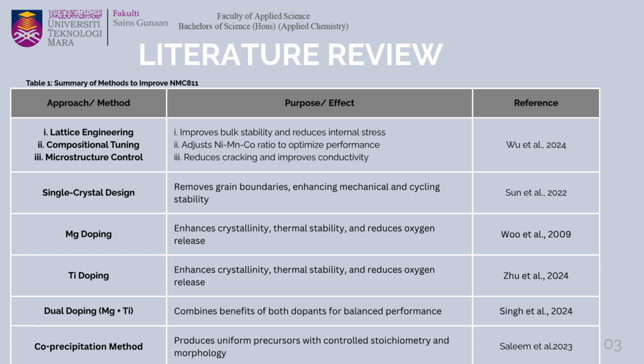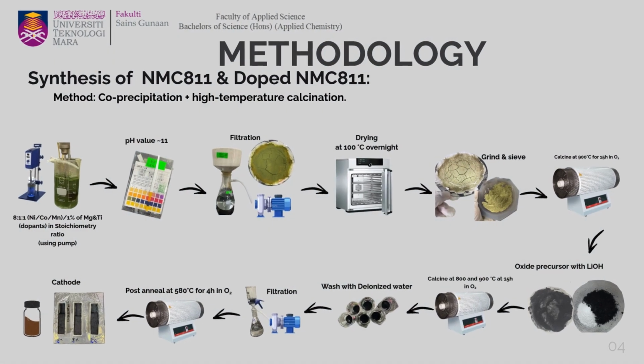Next is transitioning from the polycrystalline to single crystal design. A study by Sun and Liu helps to eliminate grain boundaries that often serve as sites of degradation. Magnesium dopants help to reduce lithium-nickel cation mixing, and titanium dopants improve the crystallinity. So, recent studies exploring dual doping, such as combining magnesium with aluminium or titanium, allow better control of lattice strain and improve the cycling stability. And the last one is the co-precipitation method that was reported by Salim to be effective in producing phase pure and uniform cathode materials. Okay, for the next slide is methodology.